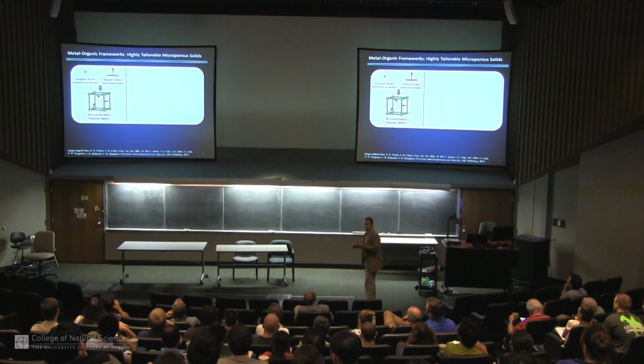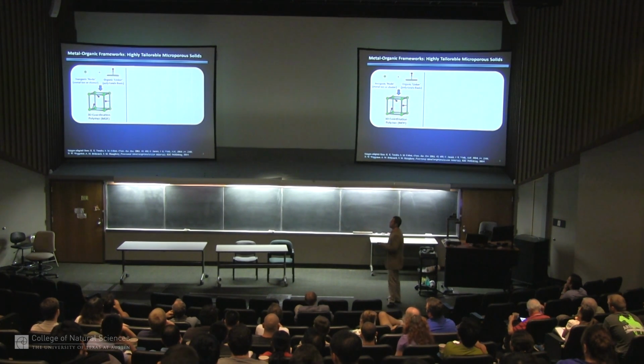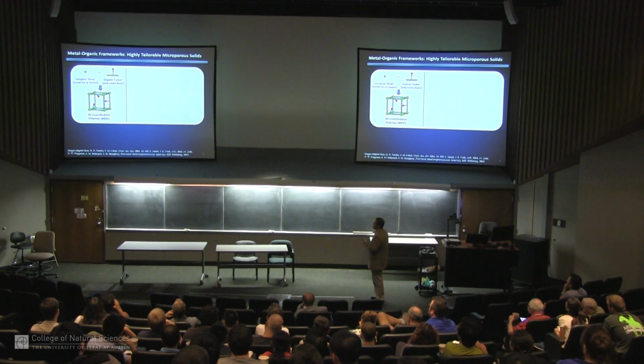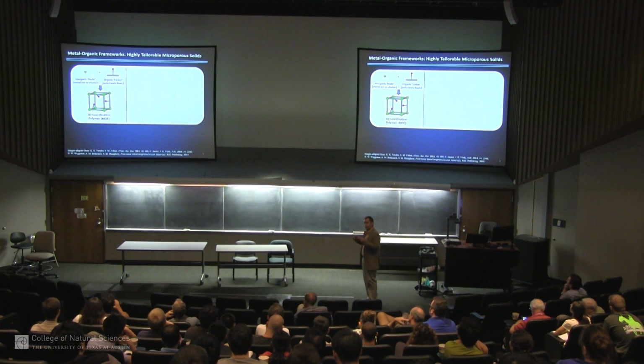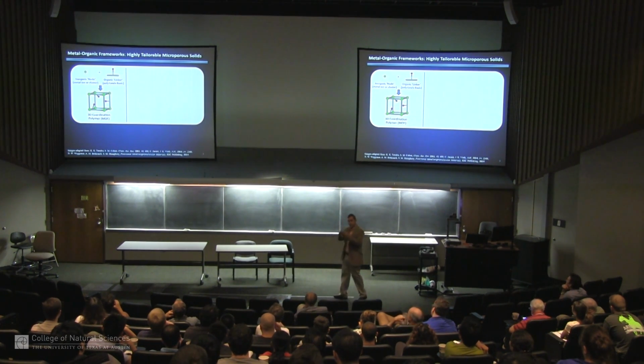The coordination bonds are easy to control based on the way the metal wants to bind to the ligand. And although this is very cartoon-like, you can see if you have a functional group on this linker, you can dangle that into the pore. So now we construct a porous polymer, and anything that enters this pore, a guest molecule, is going to see these functional groups. And this makes these materials more flexible and more designable than a zeolite, a naturally occurring porous material, because we can decorate the cavities of the pores.